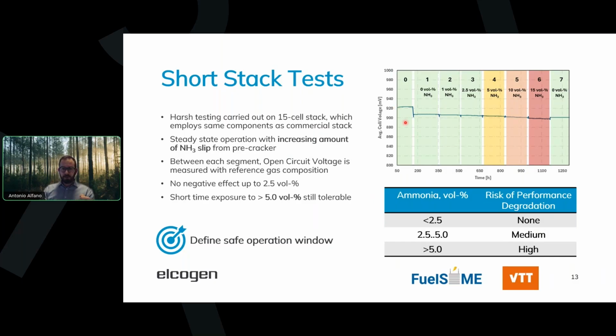What we have done here, we have kept the stack under current. So this is the voltage, average cell voltage kept over time, and we have gradually increased the amount of ammonia that was fed to the stack by keeping fuel utilization constant through mass flow controllers, adjusting the hydrogen flow rate. In between every step, you see this blank space. This is where we were doing basically a reference measurement at open circuit voltage to check the gas tightness of all